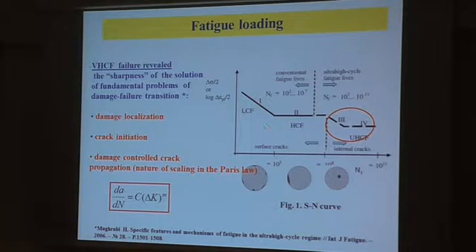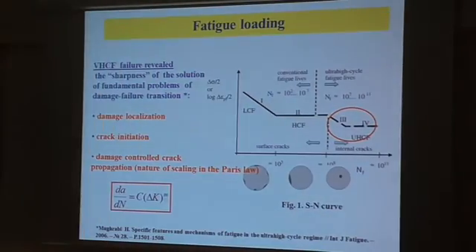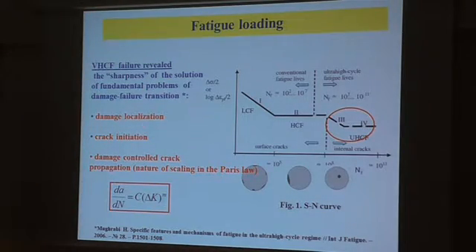I would like to attract your attention and emphasize again this long-discussed subject concerning the saturation effect of gigacycle fatigue. And I'm very sensitive to the remarks by Mughrabi, that very high cycle failure reveals the sharpness of the fundamental problems of the damage-failure transition at all, not only concerning fatigue loading, but concerning characteristic stages of damage localization, how it links with crack initiation, and how it is typical for very high cycle fatigue, where damage controls crack propagation, related of course to the understanding of the nature of scaling laws, including the Paris law, that could be generalized for very high cycle fatigue.